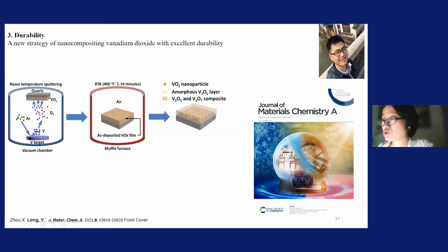Zhou Xing is one of my collaborators and also a visiting student from Sichuan, and they came up with this way, trying to work on this using the PVD way, and came up with a very simple idea. Use rapid thermal annealing to deposit this VO2 still embedded in V2O5 and V3O7. Why is this one good? Because V2O5 and V3O7, these two are the thermodynamically stable phases at room temperature. So by using a very special way, they get very durable VO2 films, and